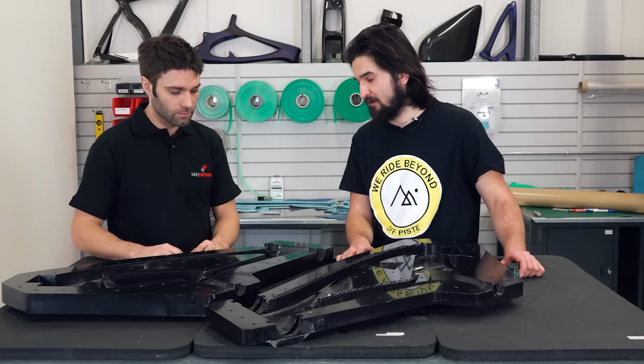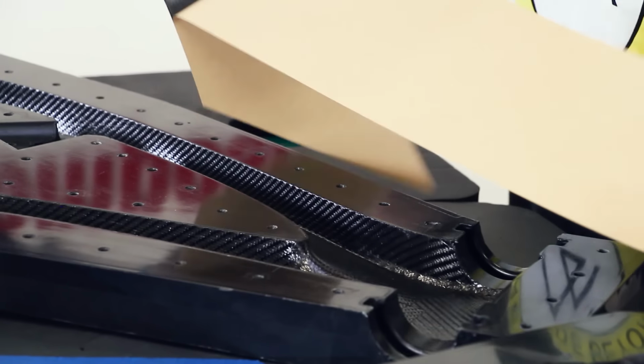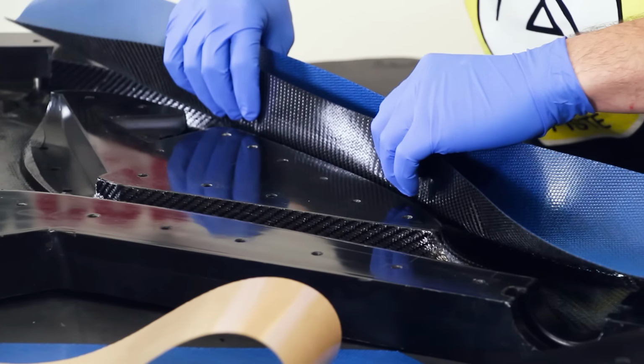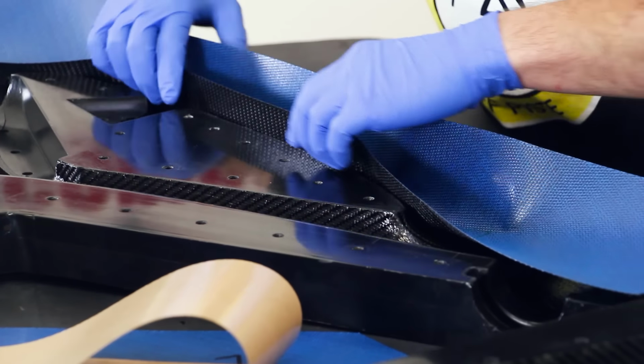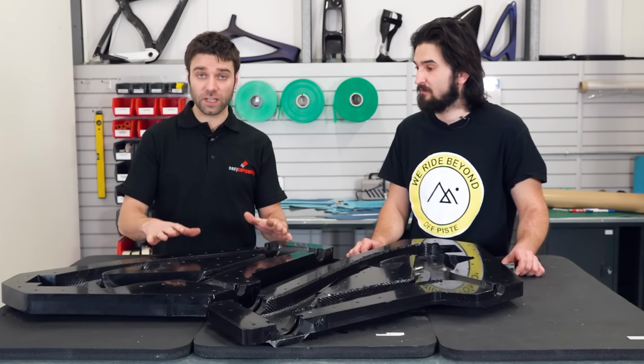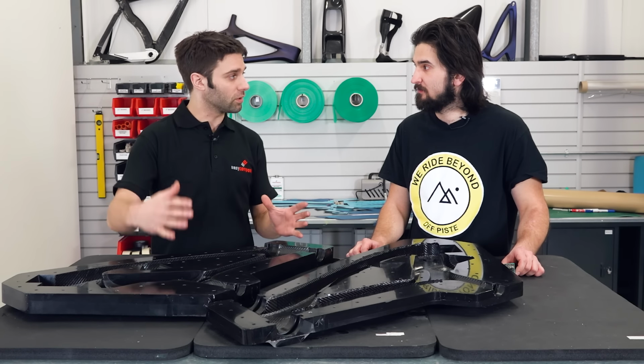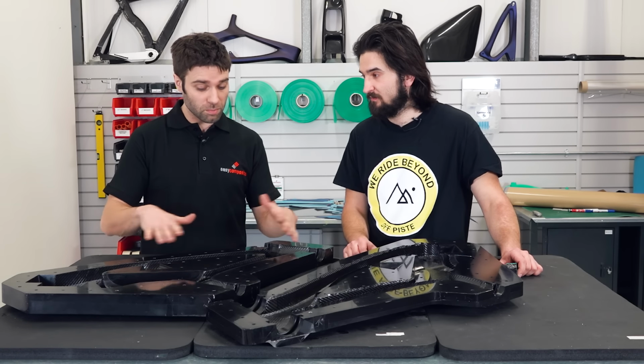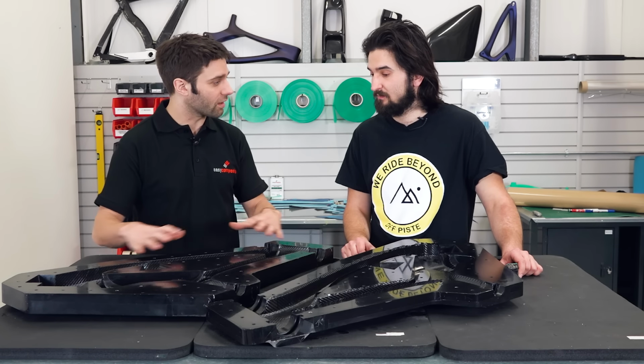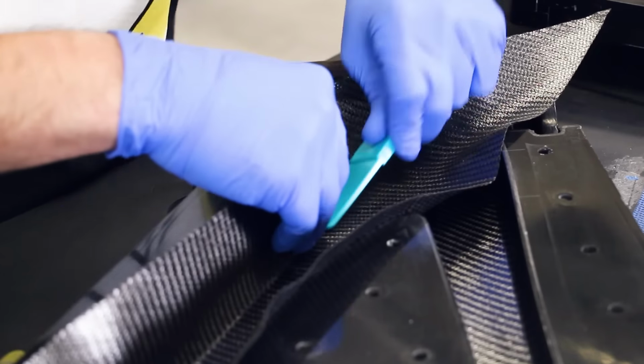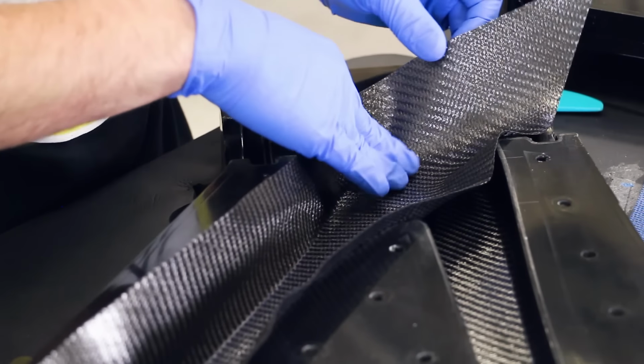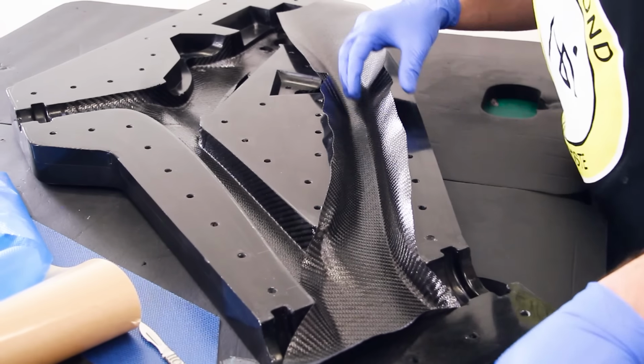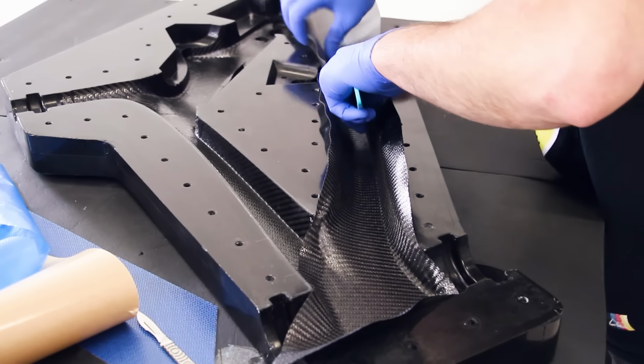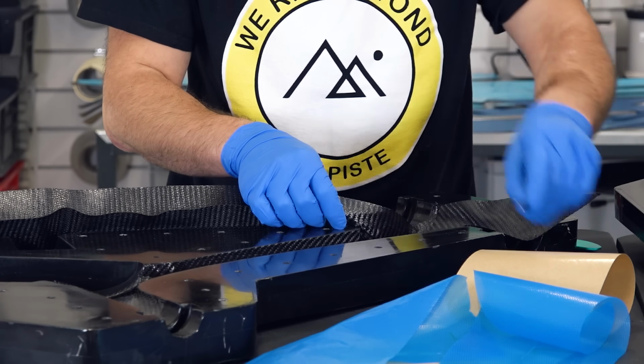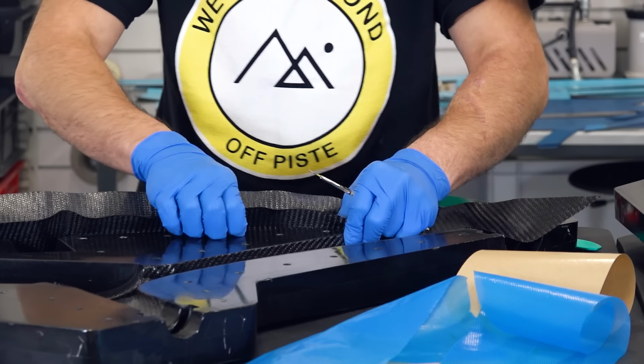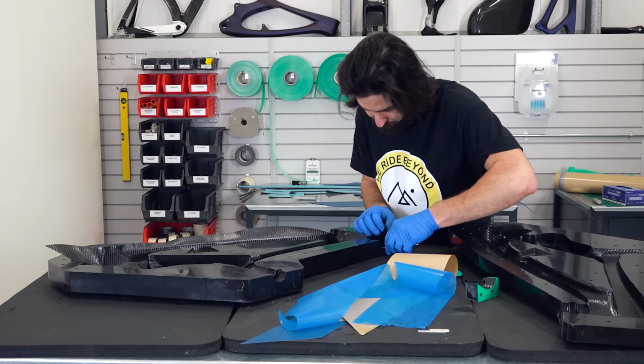Well, it's the second ply, which is again, we use 210 gram twill. But it's going to sit at plus minus 45 degrees. Essentially just the same as this first layer, but we're using the same material, turned around through 45 degrees, presumably just to give it more even strength throughout. Yeah, it just strengthens the skin. The second ply is laminated in just the same way as the first. The 45-degree orientation increases the torsional stiffness of the tube prior to the unidirectional plies that will follow.